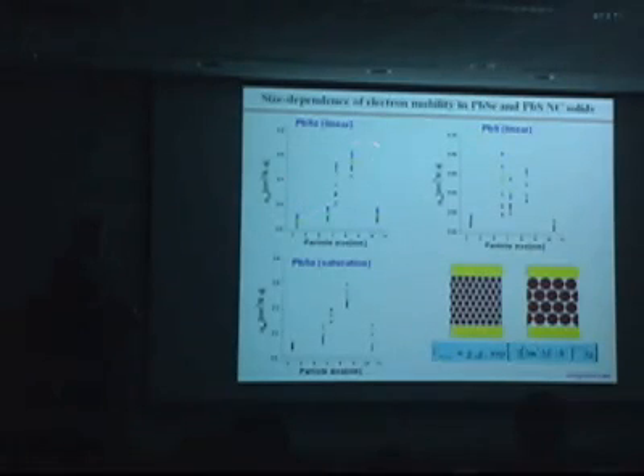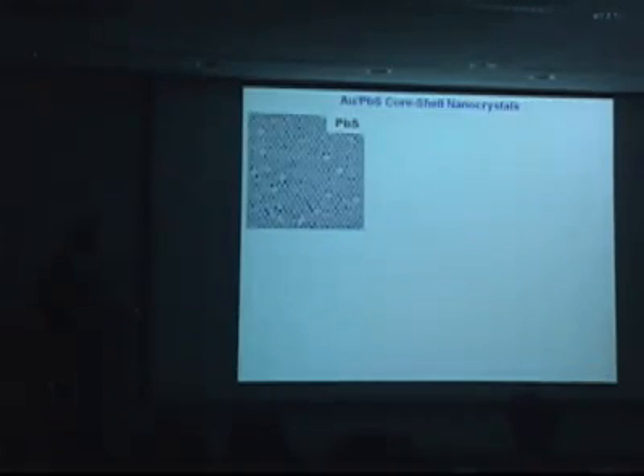For example, we clearly see that we have an optimal size for mobility. It goes down on both ends, and so in FCC arrays of nanocrystals, the optimal size is about 8 nanometers, and it applies to many systems. We don't quite understand what the physics behind it is yet, but as chemists, we can try some more interesting or weirder things, because just an array of, for example, lead sulfide particles is a very neat example of a nanogranular electronic material. And in principle, it is well described by existing theoretical frameworks.